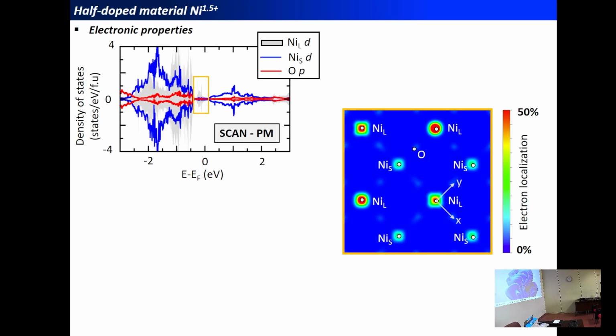If we look at the partial charge density associated with these states, we see that it is localized on the nickel cations. But what you can see, in contrast to the bismuthate, is that there is no oxygen contribution there. And so it's mainly dominated by the nickel d states in this material. Nevertheless, maybe, I'm not sure if you see further away, there is no gap in the material. But this is due to the fact that our DFT functional does not correct sufficiently the self-interaction error, and so, as in highly correlated semiconductors, it can underestimate the band gap.